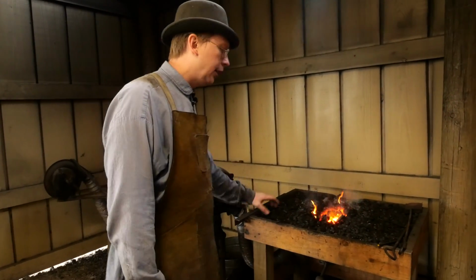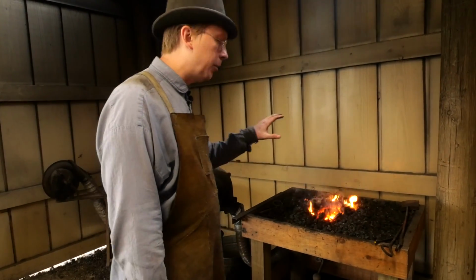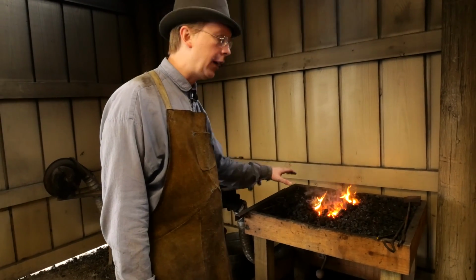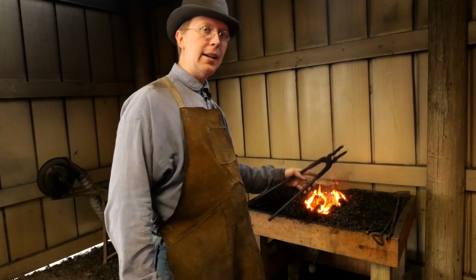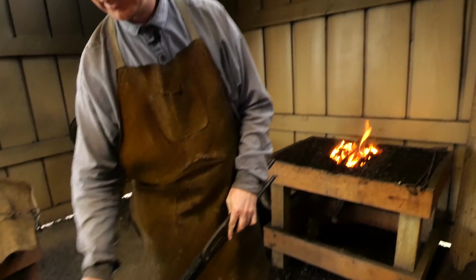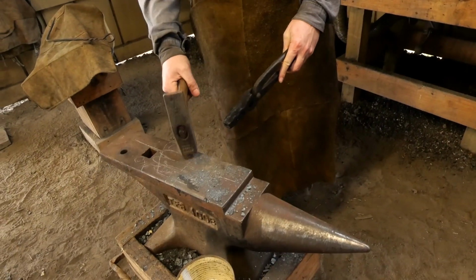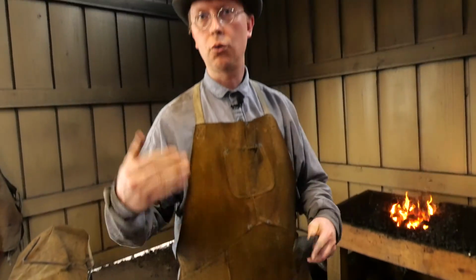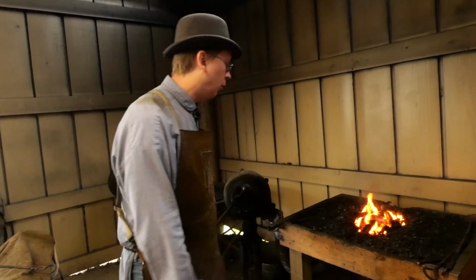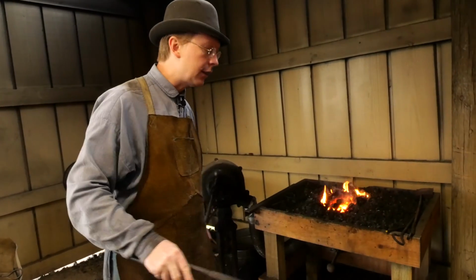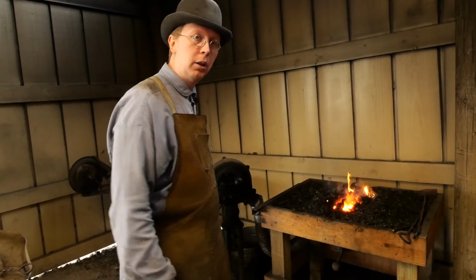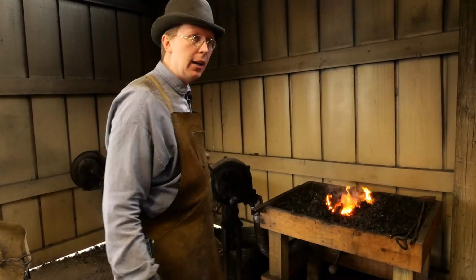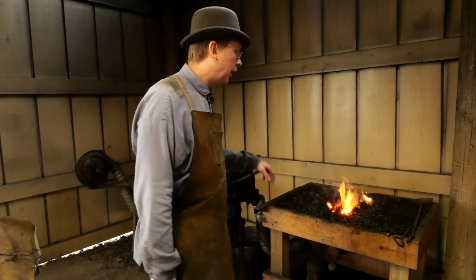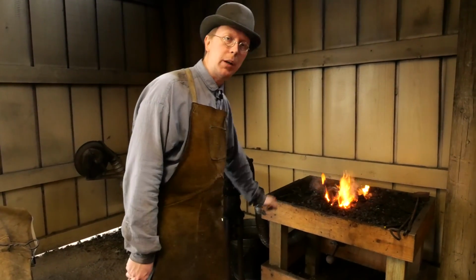Like I said earlier, if you're struggling with the forge welding, it's probably because your steel is not hot enough when you're coming out of the fire, or you're dilly-dallying as you come over here and find your anvil, and you finally get in to give it a hit, and it's dropped below your forge welding temperature, and so you don't get a good weld. So this is a good thing to practice, that out of the fire onto the anvil, and a firm yet not overwhelming hit while it's cold and you don't have the pressure of the forge weld.